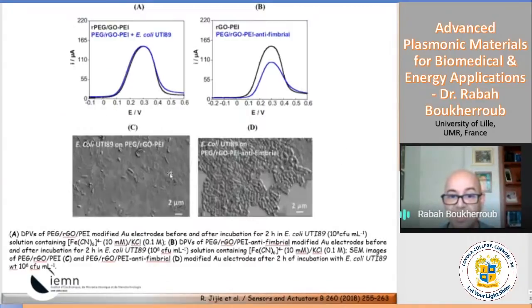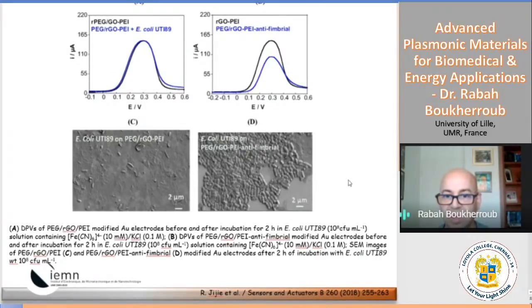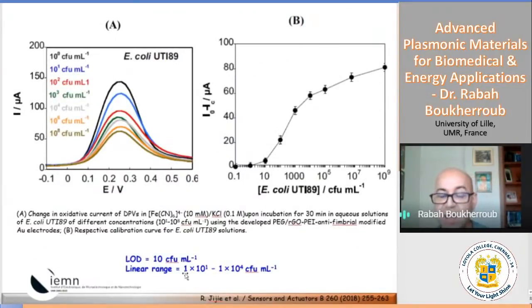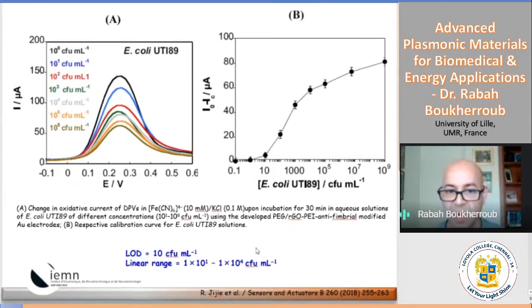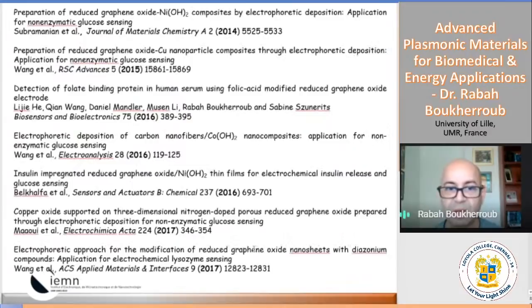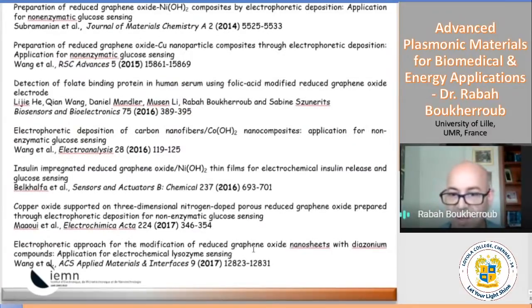And you can see if I don't functionalize the polymer with the antibody, there are no bacteria on the surface. However, when I functionalize that, I capture all the bacteria in the sample. So we can really have a very selective and sensitive capture and detection of bacteria using an electrochemical method. And they can reach down to 10 bacteria per ml, which is really very sensitive. In some examples you can probably get to one or a few, but it's still very sensitive given the way the sensor was made.